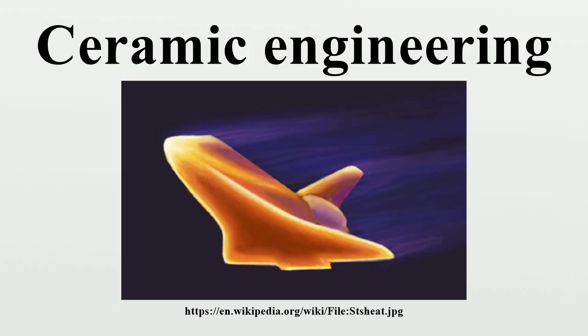Tape casting or forming processes are also of increasing interest for other applications, ranging from open structures such as fuel cells to ceramic composites. The other major layer structure is coating, where melt spraying is very important. But chemical and physical vapor deposition and chemical methods are all seeing increased use. Besides open structures from formed tape, extruded structures, such as honeycomb catalyst supports, and highly porous structures, including various foams, for example, reticulated foam, are of increasing use. Densification of consolidated powder bodies continues to be achieved predominantly by sintering. However, the use of pressure sintering by hot pressing is increasing, especially for non-oxides and parts of simple shapes where higher quality is needed, and larger size or multiple parts per pressing can be an advantage.